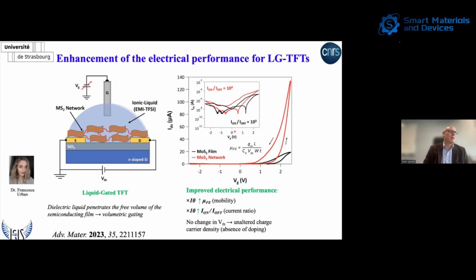And I want to jump directly to how we can use this to improve the electrical characteristics of our material, of our film. And so we use a liquid gated transistor because in this case we can use a dielectric liquid that penetrates the free volume of the semiconducting film. And so the bottom line is that upon network formation, compared to the film, we have a tenfold increase of the field effect mobility, a tenfold increase of the on-off ratio, and we have no doping effect, at least that we perceive, because the threshold voltage remains unaltered.